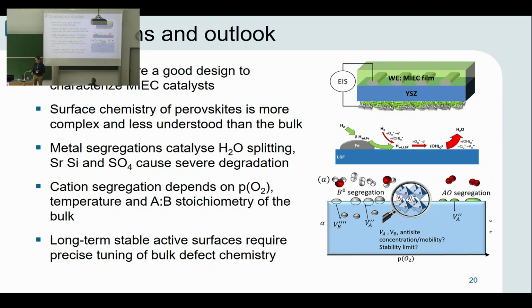And we have shown that the cation segregation depends very much on the oxygen partial pressure and the A to B stoichiometry in the perovskite as well as the temperature. And we need to understand this more to achieve more stable perovskite surfaces and get more information on the actual atomic reaction mechanisms.